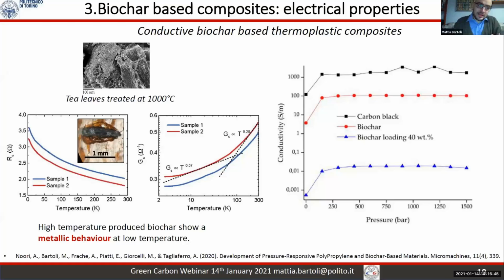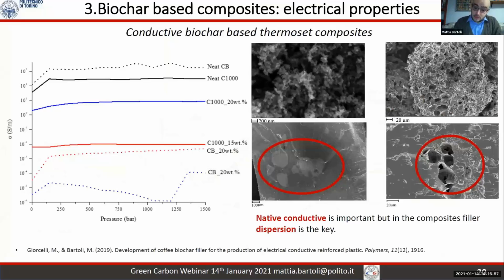The reasons behind this phenomenon are practically due to the dispersion of the material inside the polymeric matrix, and it is quite appreciable in this case. Here you can see different dispersion inside an epoxy matrix of carbon black and biochar. In the case of carbon black, you can see some islands of filler inside the composite, while biochar from coffee is well dispersed.